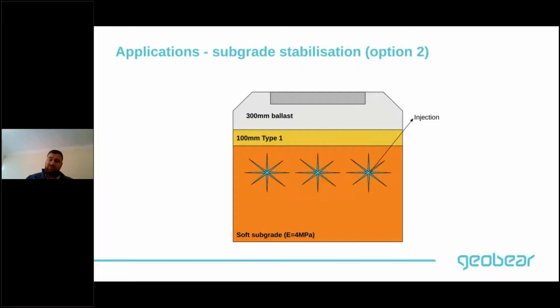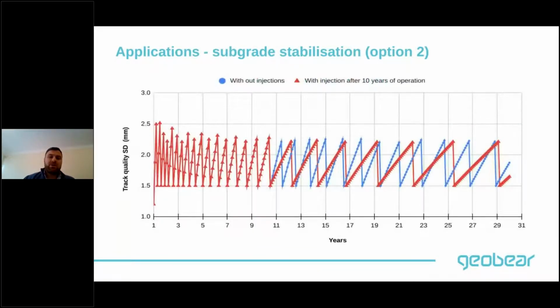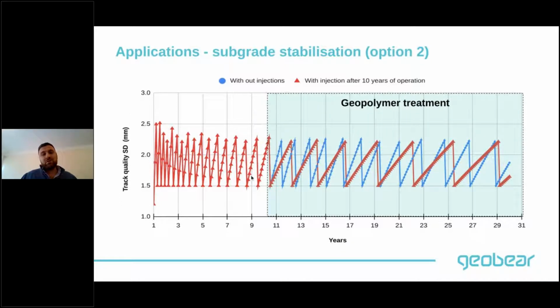However, instead of keep tamping and waiting for the track to reach its end of life completely, you can come in midlife and intervene, inject the geopolymer, stabilize the track and reduce the rate of degradation. So here, just to show you two graphs, the track quality time history before and after the stabilization, supposing that you decided to go with the geopolymer stabilization after 10 years of operation. So after 10 years, you decided to intervene with geopolymers. What happens? Before the intervention, obviously the track will deteriorate the same. But after we intervene, you can see there's a significant reduction in the rate of deterioration. And as a result, you're going to reduce the amount of tamping cycles that you have.